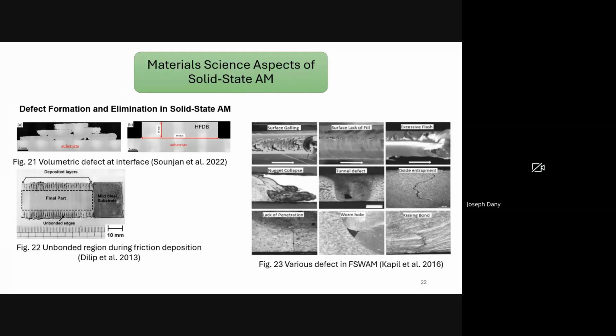Then the weld nugget can become collapsed or deformed due to improper heat input or low material flow. Then there are tunnel defects, cavities or long voids within the weld caused by insufficient heat input and plasticization, leading to material not fully flowing or filling the weld zone.